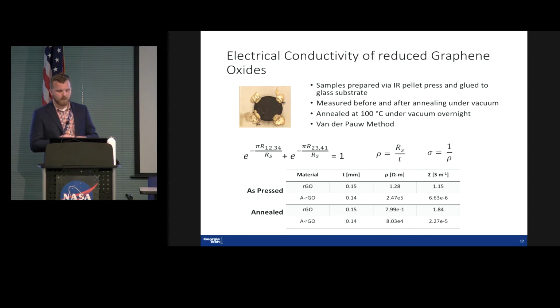And unfortunately, if we look at the column down here on the bottom right, that is the conductivity of these composites. And we see that there's a factor of about 1 million difference in conductivity between the alkylated version and the regular reduced graphene oxide. What this means is that our alkylation has compromised the integrity of the sp2 carbon plane that is generally associated with the high conductivity that we would normally see in graphene.